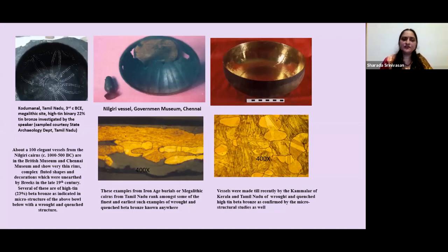And I had also analyzed a vessel from Kodumanal, which is a megalithic site, which is also a high-tin binary 22% tin bronze. Well, it's also interesting that vessels have been made till recently by the Kammalar, or bronze smiths, in Kerala and Tamil Nadu of hot forged, quenched high-tin beta bronze, which has also been confirmed by microstructural study. And you can see on top this modern vessel, which myself and Digvijay documented in the 90s, where this ingot of 15 centimeters has been extensively forged out to get these large vessels. And then it's been polished to get this very brilliant finish, this golden luster, which is why these were sought after. And some of these examples from the Nilgiris and Adichanallur and so on go back to about the early to late first millennium BCE.